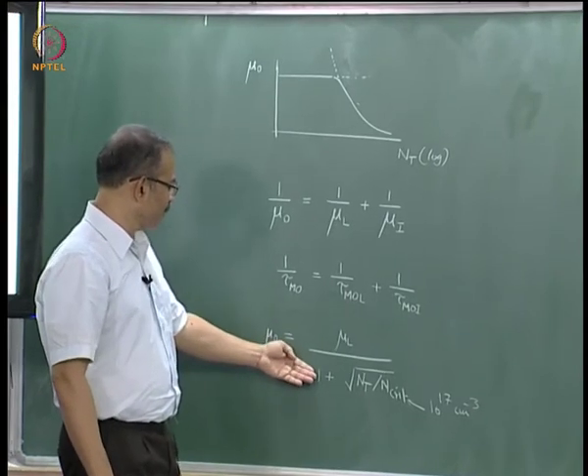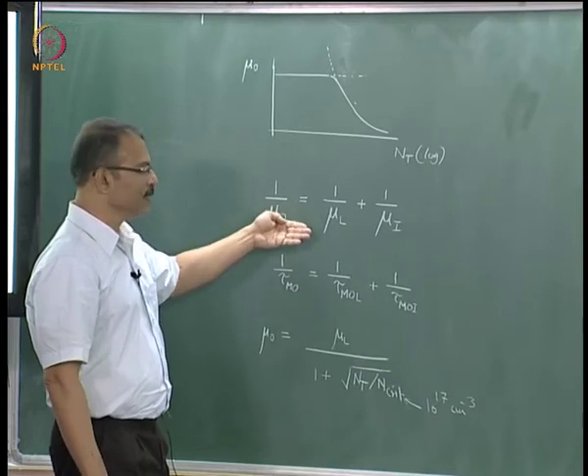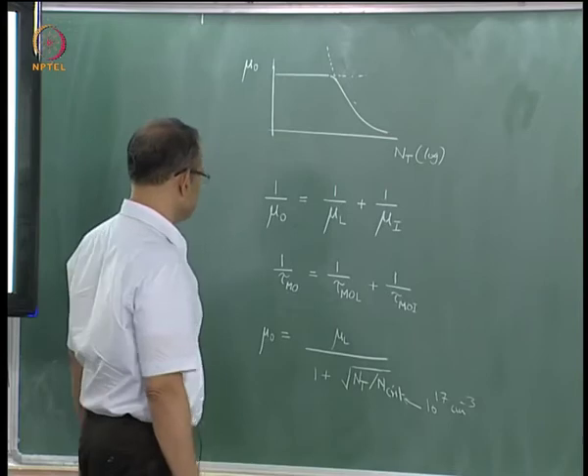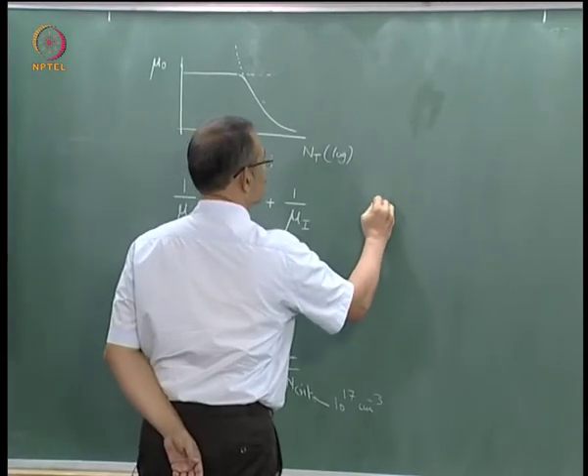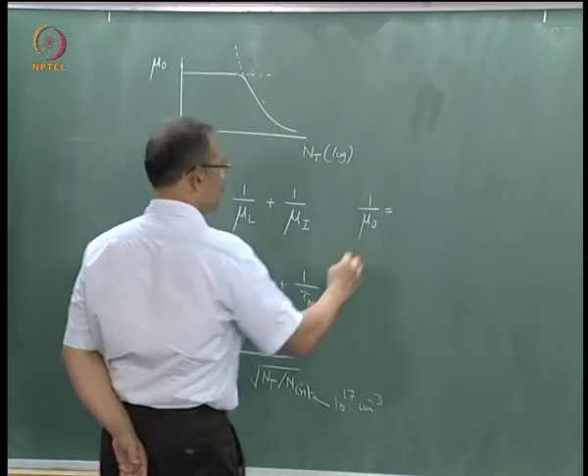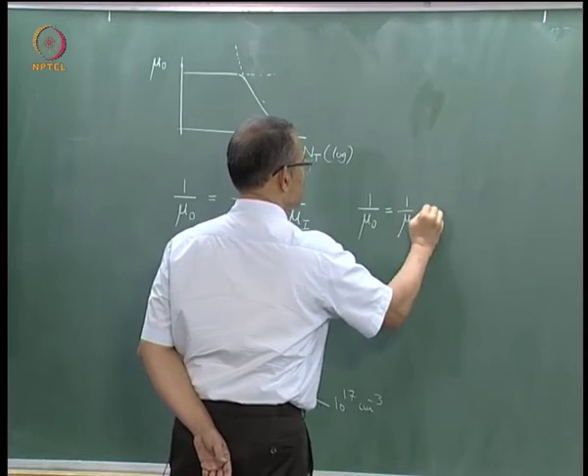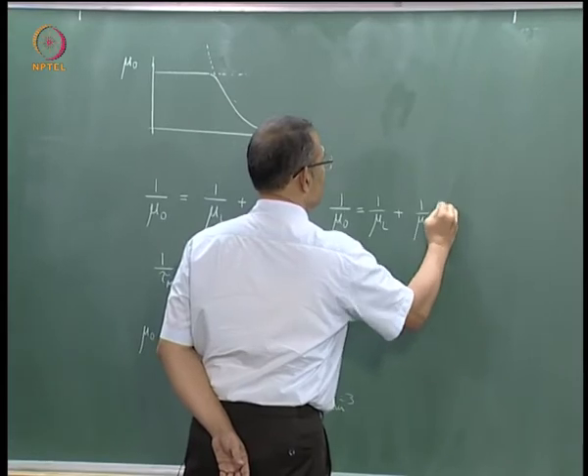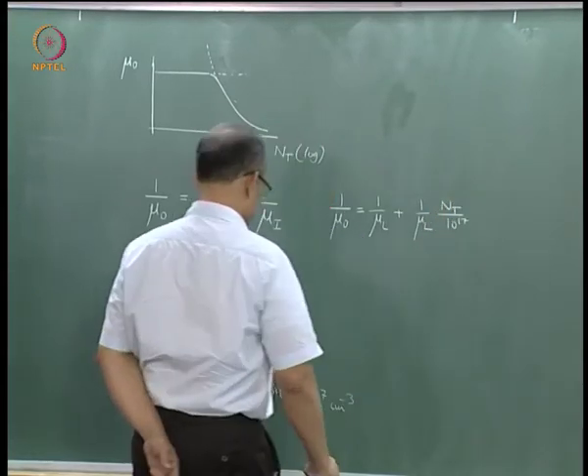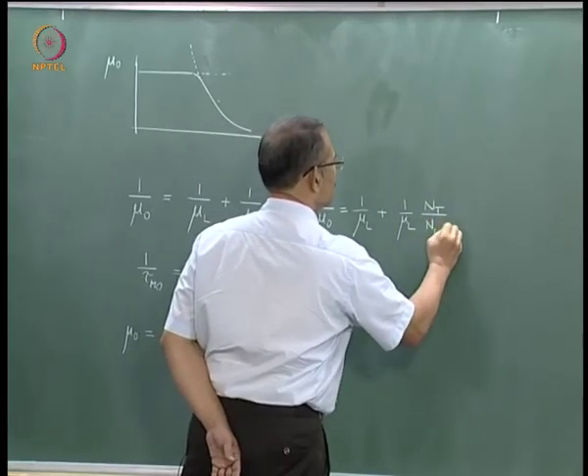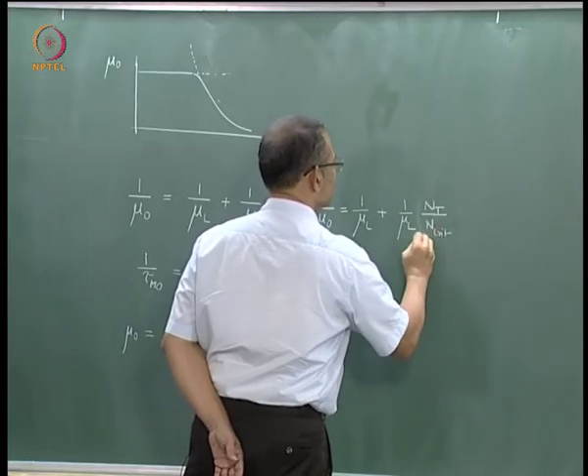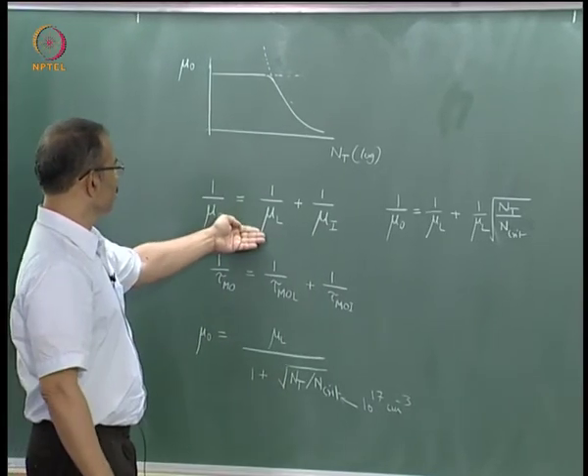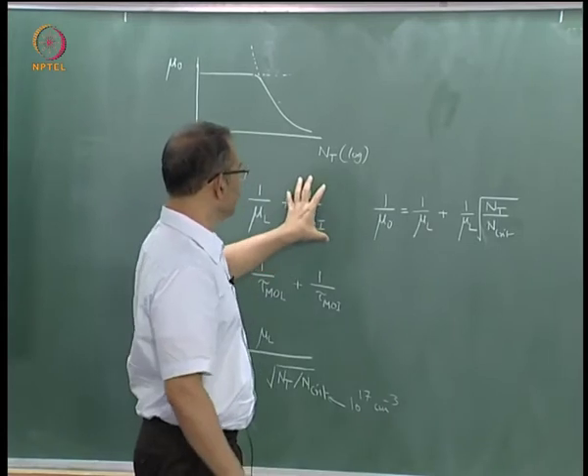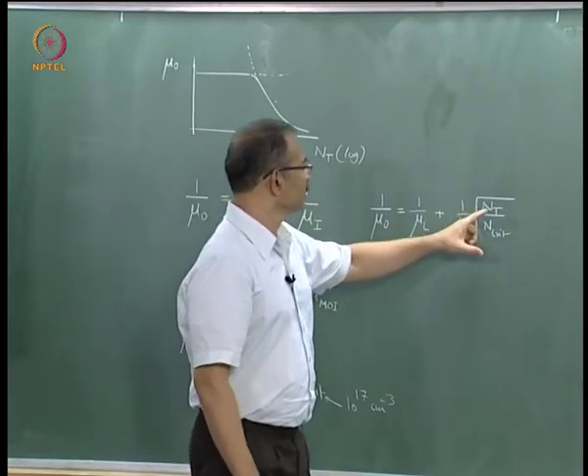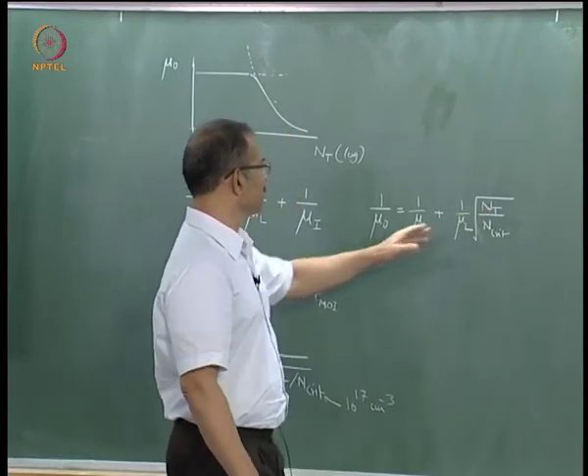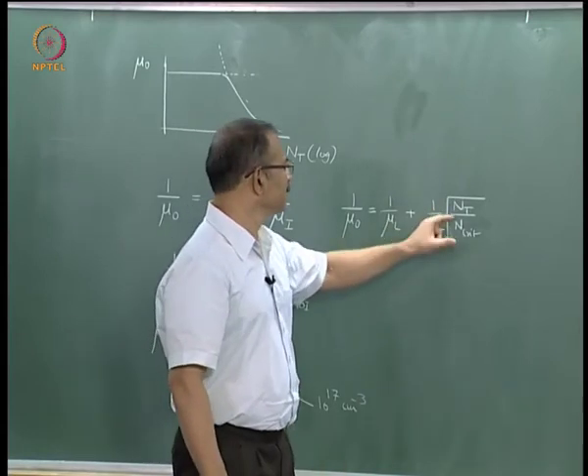Now let us cast this formula in this form, in reciprocal form, and then it will be very evident how you get the relation. So when I cast it in reciprocal form, it would look as follows: 1 by mu naught is equal to 1 by mu L plus 1 by mu L into square root of Nt by N critical, of course with a square root sign. Now you compare this formula and this formula. So what you find is we have written an expression for ionized impurity scattering. So we have said the ionized impurity scattering goes on increasing as square root of Nt, and then this is nothing but a constant.